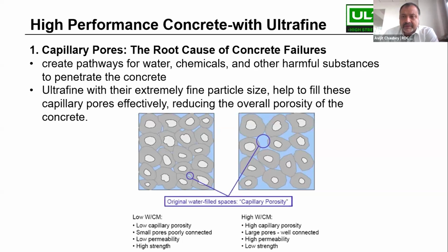Also, because there were no admixtures at that time, we had to use a higher water content for the same cement content, and we ended up getting much lower strengths than the potentially possible strength. This happens because at a higher water cement ratio, the cement particles are very far away from each other. If you see the right side picture, it is a model which shows a typical concrete with a very high water cement ratio, whereas on the left hand side it is a high strength concrete with a very low water cement ratio. Too much cement, but very little water. This movement from right to left is the traditional method of increasing the strength.